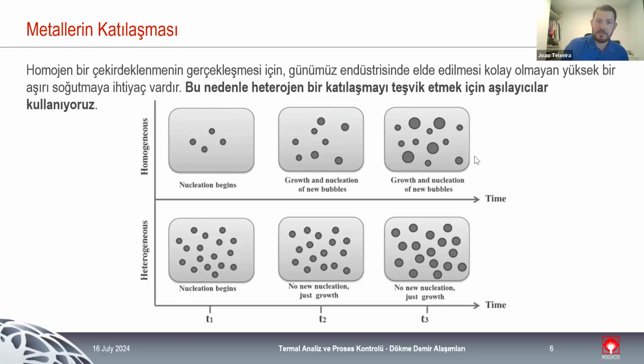So again, it's a second part of the importance of inoculation, which is to achieve a quicker solidification by adding stable nuclei for the nucleation to happen, and to allow time for the carbon to transform into graphite and not into carbides. So inoculation has these two different important aspects. And in this image, we can see the big difference between having a heterogeneous nucleation and a homogeneous one. At the end of the heterogeneous nucleation, you can see that we have a lot more stable nuclei compared, at the same time, with the homogeneous one. So inoculation is a really, really important step in cast iron production, mainly for the stable nuclei to be added to the liquid metal.